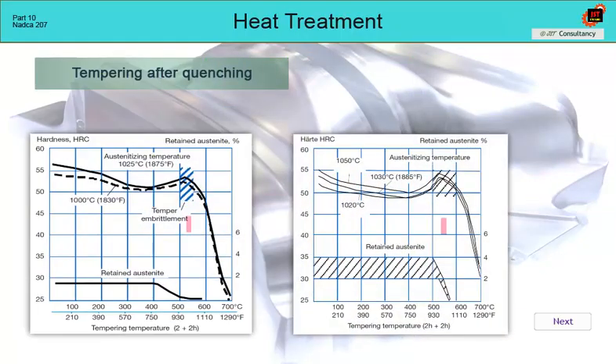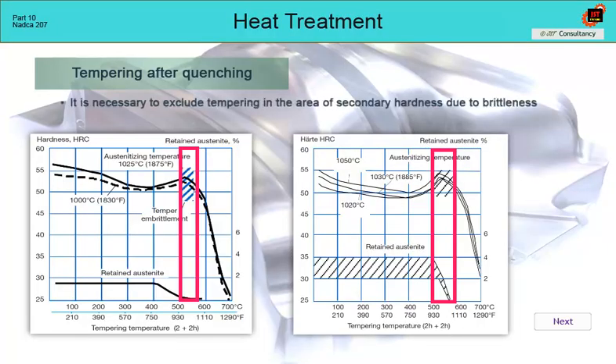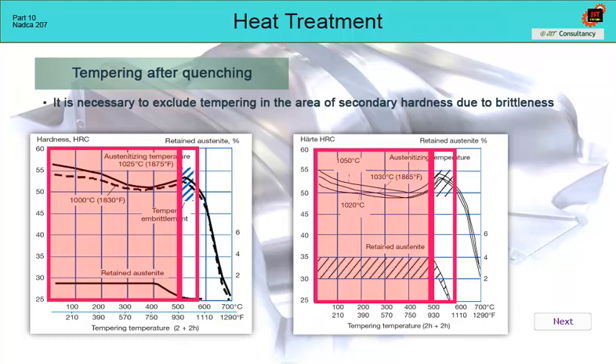The first tempering must be strictly carried out outside the secondary hardness area. In this area, due to precipitation of carbides, the material is brittle with low impact strength. Lower temperatures below 500 degrees Celsius are not suitable for hot work steels with regard to the working conditions of the mold and the temperature of the melt.